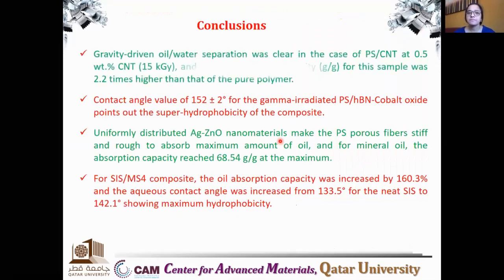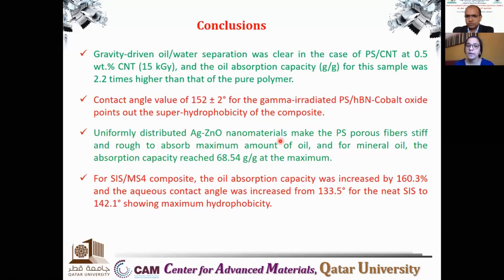Yes, conclusion. Gravity-driven oil water separation was clear in the case of polystyrene and carbon nanotube at 0.5 weight percentage of carbon nanotube. The contact angle value of the gamma irradiated composite was higher. This is because of the high compatibility of the filler and the polymer molecules inside the composite after gamma irradiation, and the uniformly distributed silver zinc oxide. We have another paper based on the porous electrospun polystyrene with silver zinc oxide, highlighting the photocatalytic application of zinc oxide. It is in this way we can make multifunctional composites. And the SIS mesoporous composite was useful for ultrafiltration experiments. So these are the different strategies that we adopted in our research for separating oil water emulsions.